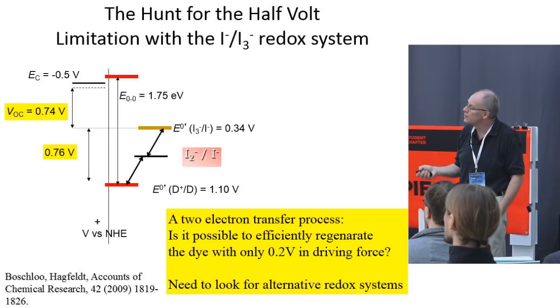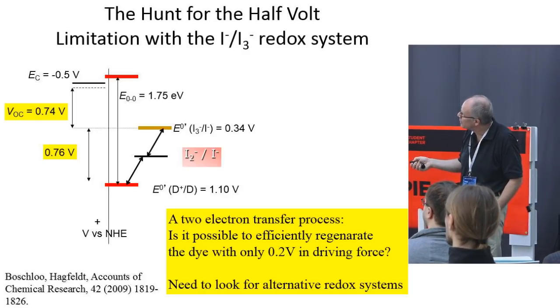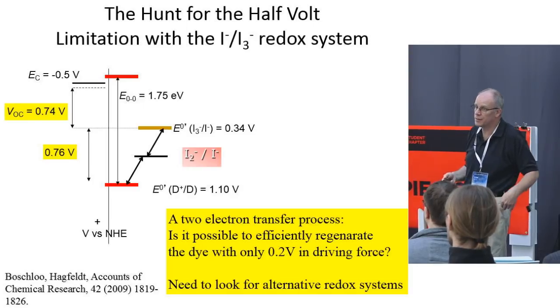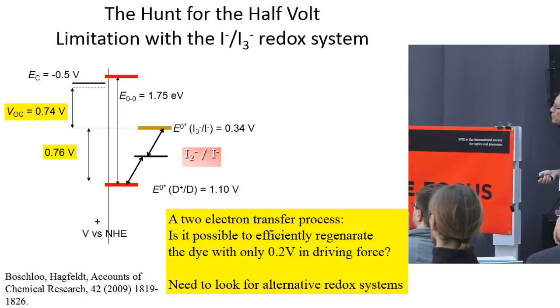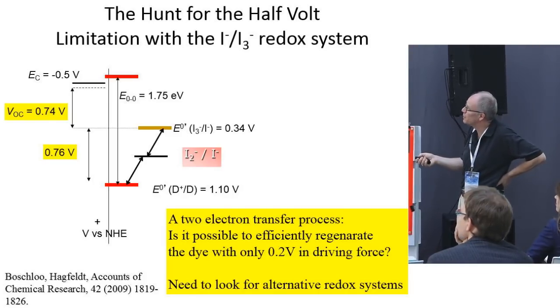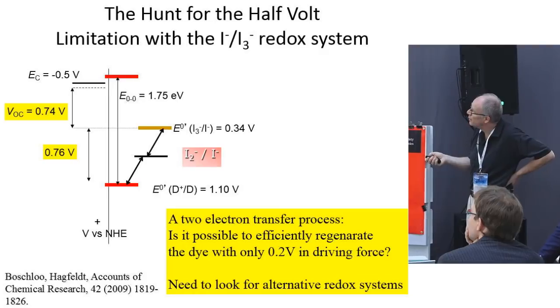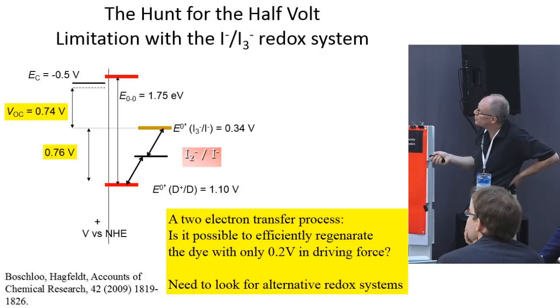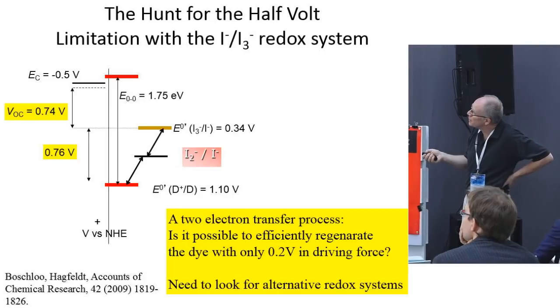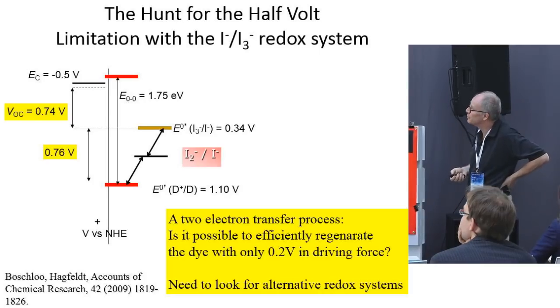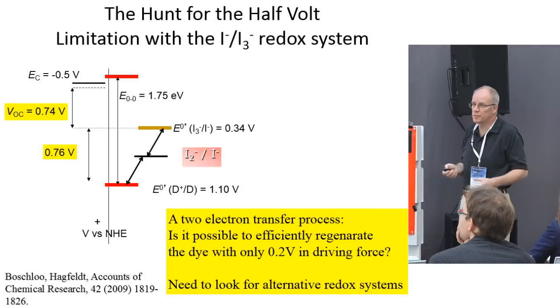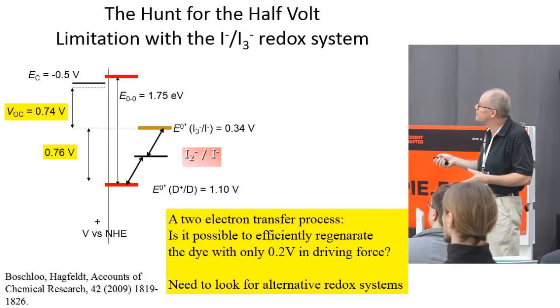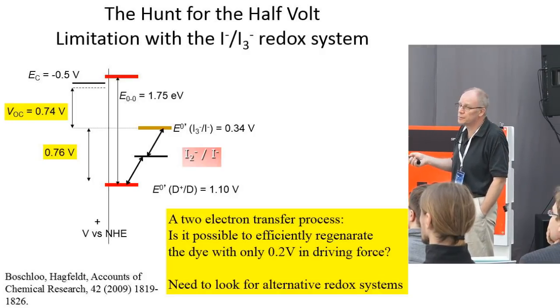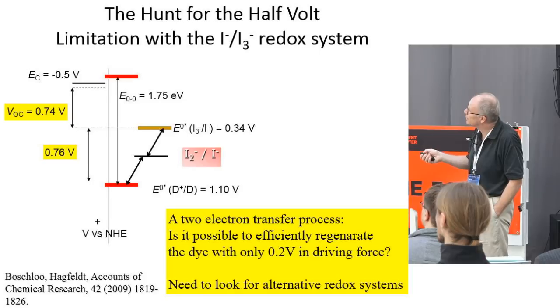So that's the drawback. So the question is, how far low can you go until you make this too slow, let's say, and you have recombination. The other problem, the reason why this was standing still for 20 years, was that for all other redox couples, if you change, you open up a recombination process. So electrons here in the TiO2 can also react with the electrolyte. And that works very well for all redox couples besides the iodide, which is not doing that. So that was a fundamental problem. When you change to something else, you have a recombination of electrons in TiO2 with the electrolyte. So you need to passivate that reaction.